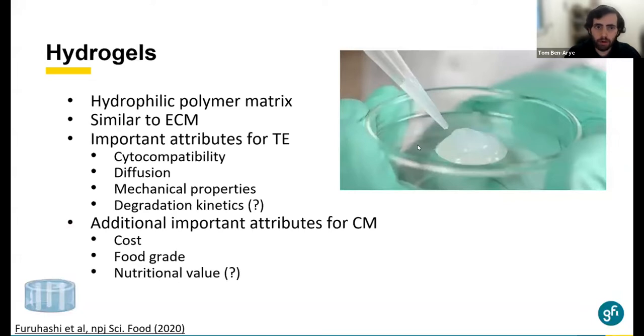Another option, in addition to the porous scaffolds, is hydrogels. In tissue engineering, we work a lot with hydrogels. They are composed of a hydrophilic polymer matrix that can absorb water, over 90% water. Hydrogels can resemble the extracellular matrix. The extracellular matrix itself is some kind of a hydrogel, and because of that, hydrogels are very interesting for our purposes. They should be cytocompatible. They should allow a diffusion of molecules through them. That's an important property of the hydrogels, the velocity of the diffusion of the molecules in it.